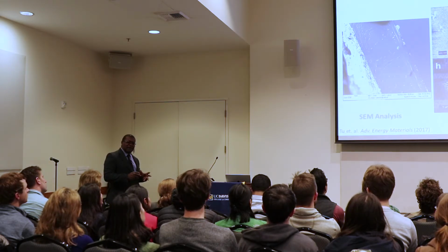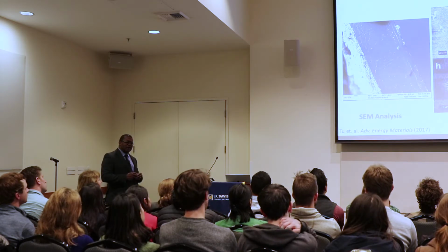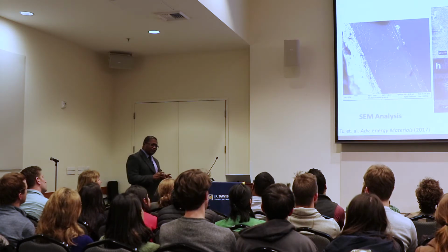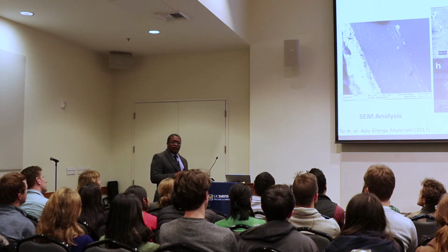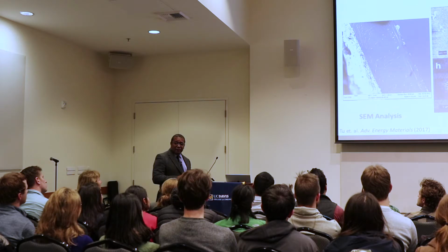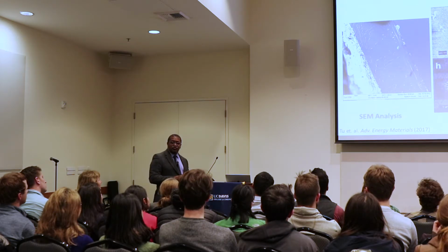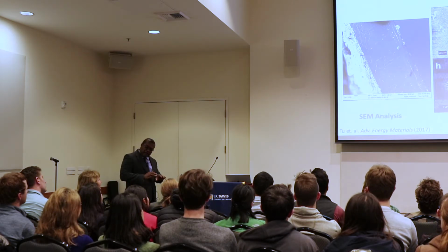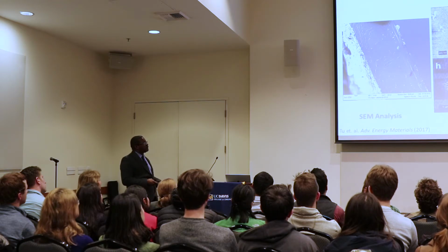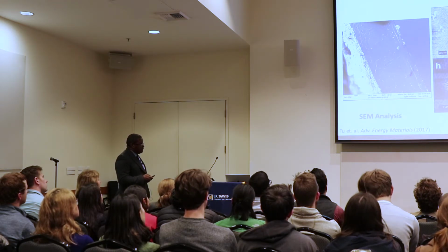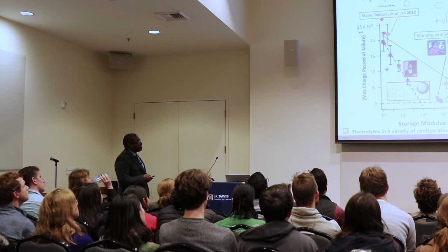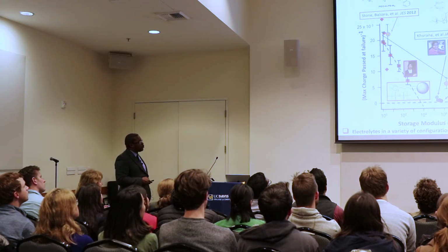So we can basically say that by controlling the length scale below a certain value, where we think surface forces like surface tension and interfacial elasticity dominate, we can essentially use natural forces to stabilize and make more smooth the deposition, in this example. Now, my students, of course, went wild.